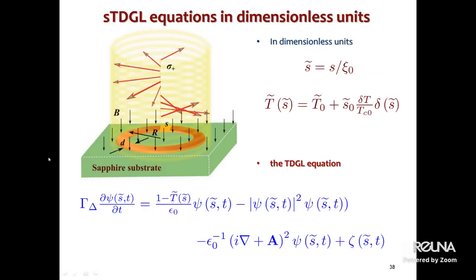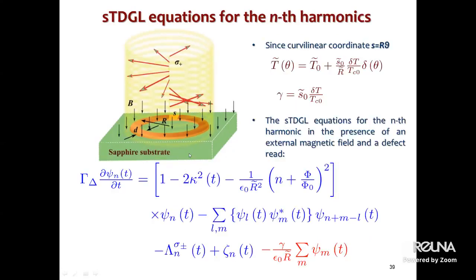And then, following the same procedure, we obtain a system of coupled differential equations for n Fourier modes of the order parameter. The stochastic time-dependent Ginzburg-Landau equation for the nth mode, including the effect of external magnetic field, is written here. The term accounting for the defect is highlighted in red. In this framework, gamma larger than 0 corresponds to a local increase of the temperature, which is equivalent to a local decrease of the superconducting transition temperature. And gamma smaller than 0 corresponds to the opposite situation.